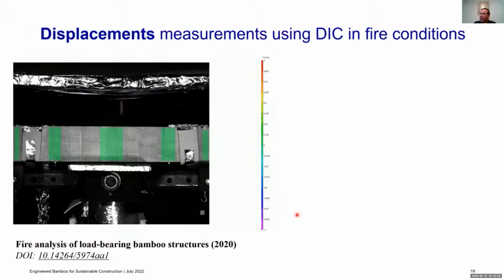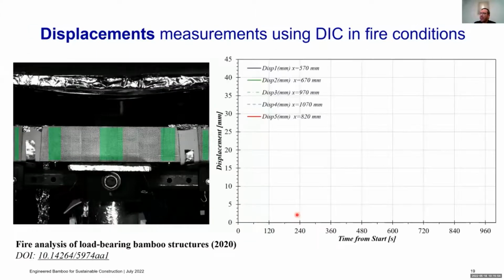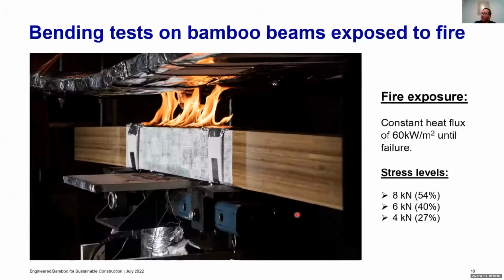This is a video that we took during the test. Again, it's a bending test. The main difference is that we ended up pushing the beam upwards. Normally on a bending test, you do it pushing the beam downwards. But in this case, we did it the other way around because it was easier to control the fire exposure, and it was also easier to protect all the sensors that we had to use.